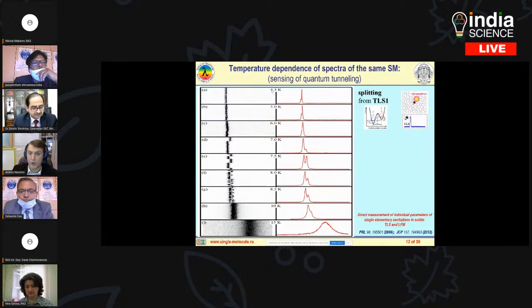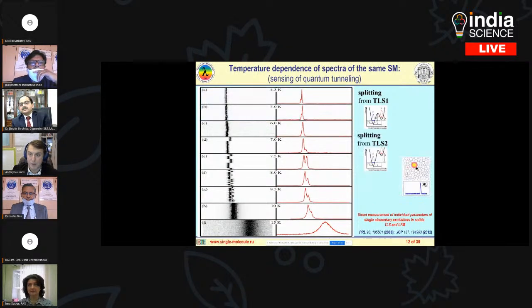And you can see, for example, at temperatures of 4 or 5 Kelvin, we see some splitting of our spectrum. It means that we have some tunneling transition close to our molecule. Thus, we have splitting of the spectrum because of a very, very fast jump of the spectrum between two positions. When we increase the temperature, let's say from 4 to 6 and 7 Kelvin, another tunneling system activates, because at higher temperature we can activate transitions over a higher barrier. Then we have a splitting between another two positions, not only between these two positions, but also another one. It means that we have activation of another tunneling system. Then when we increase the temperature, we increase the jumping rate in this tunneling system.